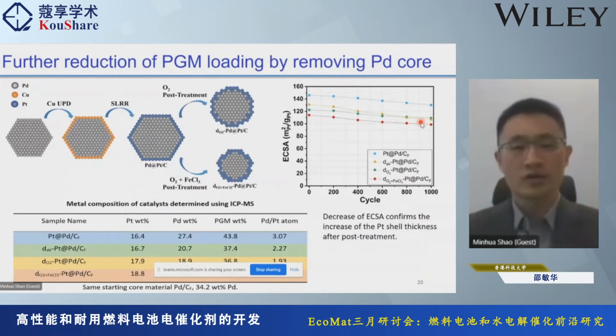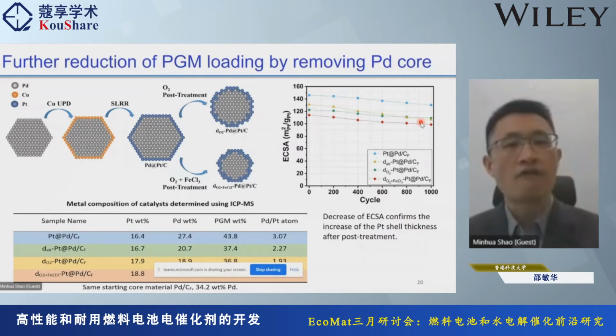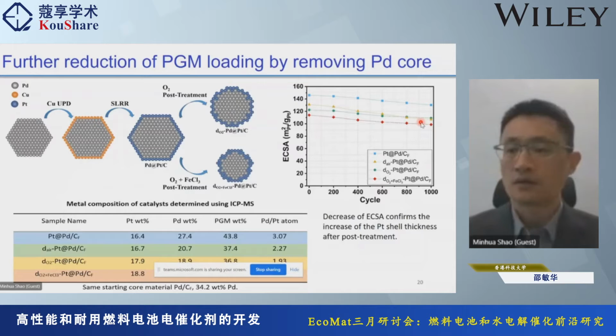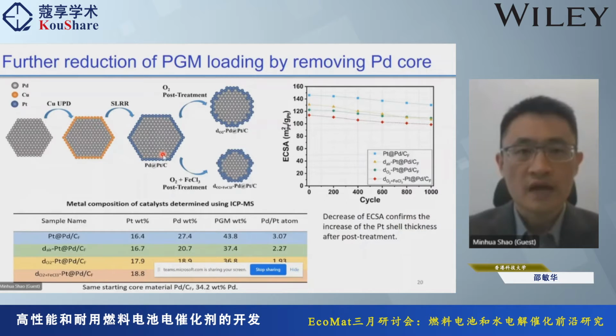Okay. Next, we are going to talk about the further reduction of the palladium inside of the core. So what we did here is that, after you synthesize this core shell catalyst, we're now using a chemical method to remove some of the palladium in the core. Okay, so there are two purposes. First purpose, of course, we try to remove some of the noble metal inside the core, palladium, to reduce the cost. Second is that after you remove some of the palladium in the core, your particle size will shrink.